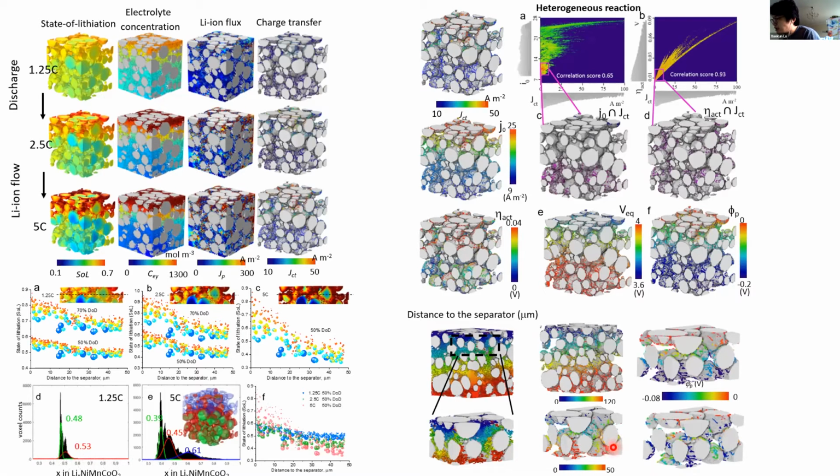As you can see here, the reacting surface is longer compared to here. Then this corresponds to here. This is a lower potential, then this gives a higher current distribution or higher exchange current. So this is responsible for the heterogeneity of the reaction.